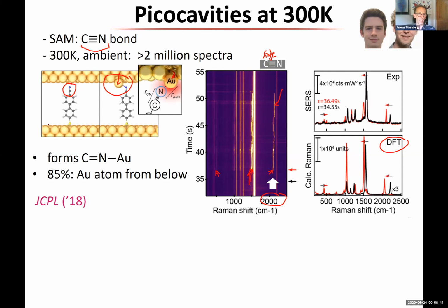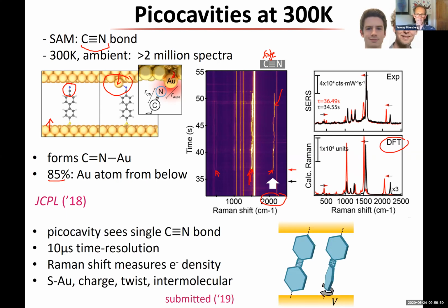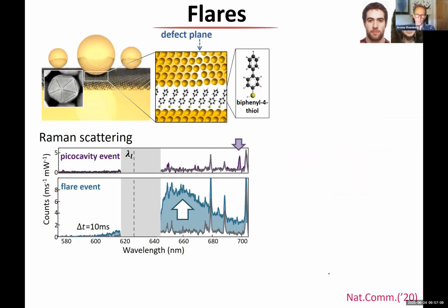We can also see that actually more of the picocavities come from the bottom metal than they come from the nanocavity, from the nanoparticle. Most of them come from the facet below. And we can do all sorts of things with this. We, for instance, now speeded up our time resolution to the scale of 10 microseconds. So we can start to see much faster, and we can start to see individual molecules flexing. So this becomes a really nice way to watch individual molecules and indeed sort of push them around.